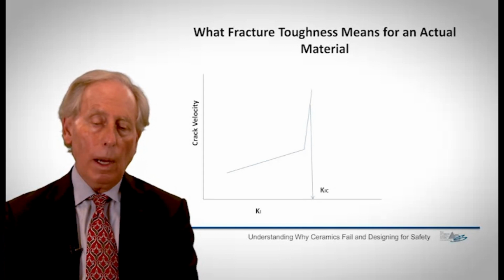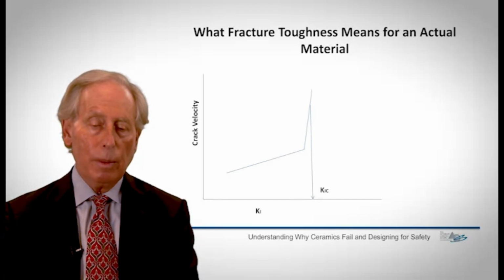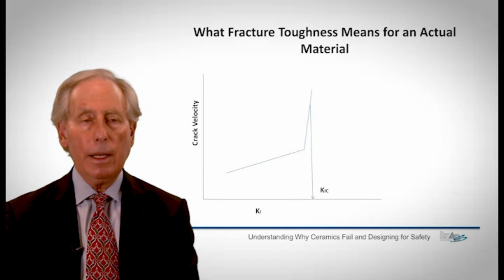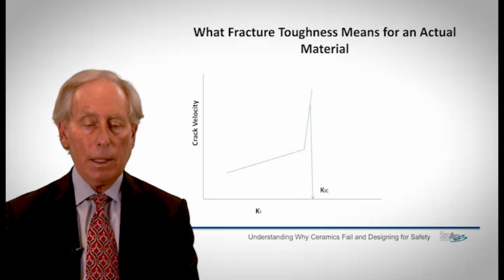And what I measure in a test like that is really where the machine can't follow the stress movement, depends on the environment, depends on the slope of the curve. This is fairly steep, so I don't make too much error depending on where it is. It typically occurs around 1/10 of a meter per second, something of that sort. But just to make the point, it's not absolutely defined. It's only defined by the test procedure itself.